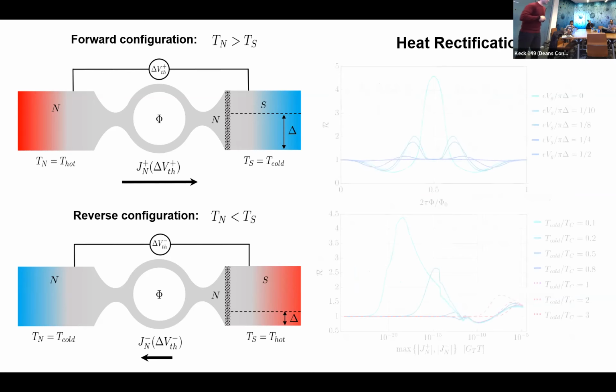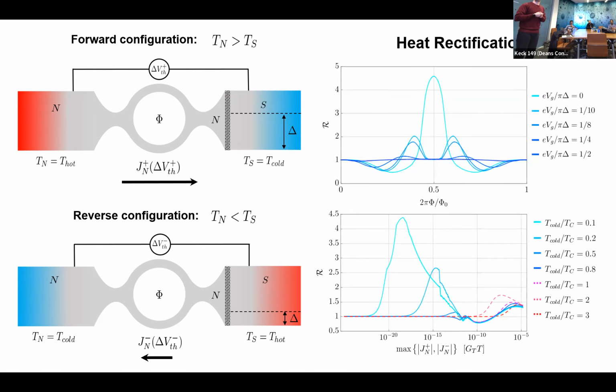Let's say that as a final result, I also want to stress that, as is the case for the power and the efficiency, we can control this rectification factor by simply controlling the external parameter. And indeed, here I represented the rectification factor as a function of the external magnetic flux. You can see that even the quality and also the direction of the rectification can be changed by changing these external parameters.